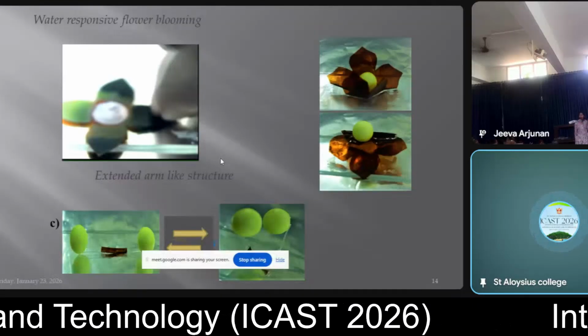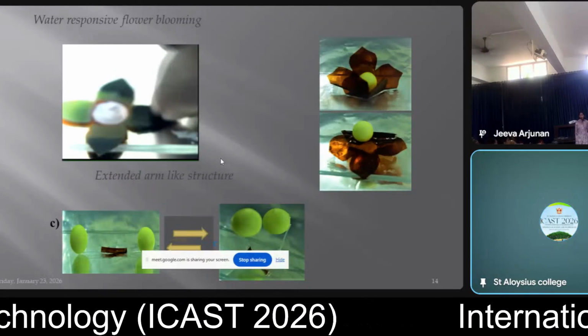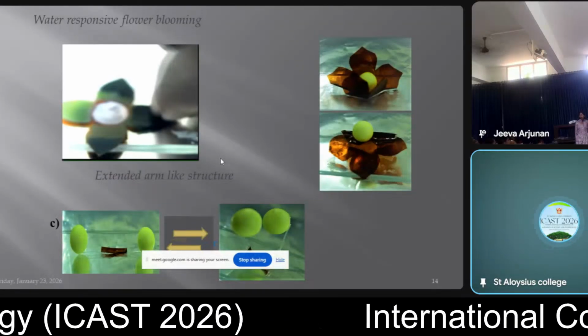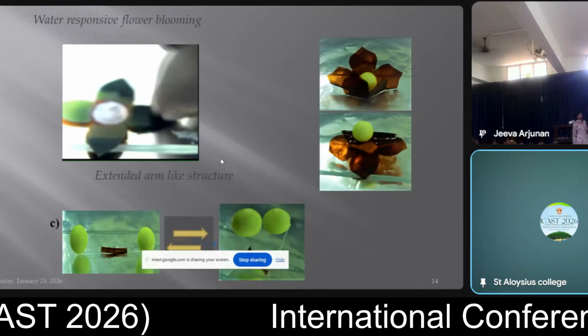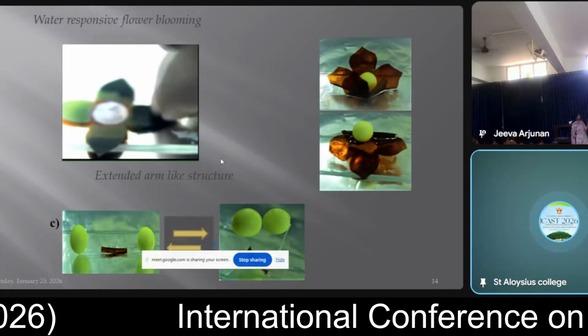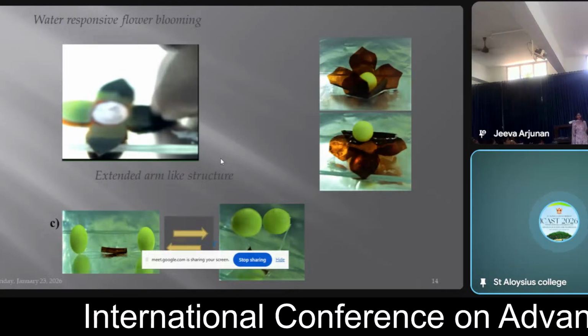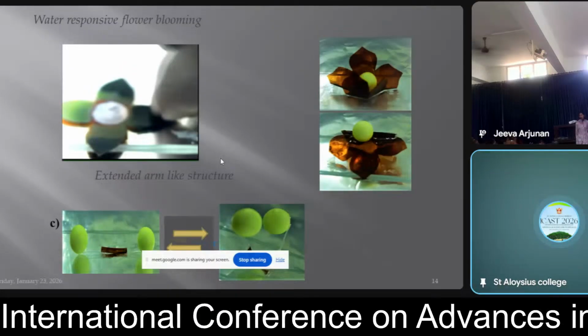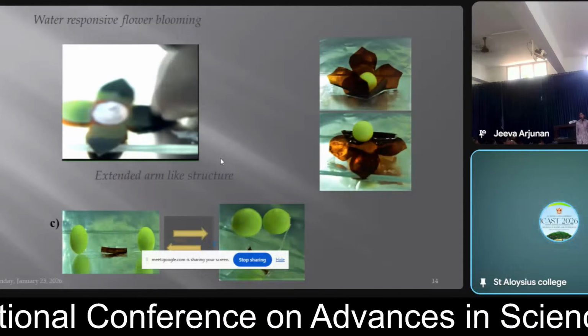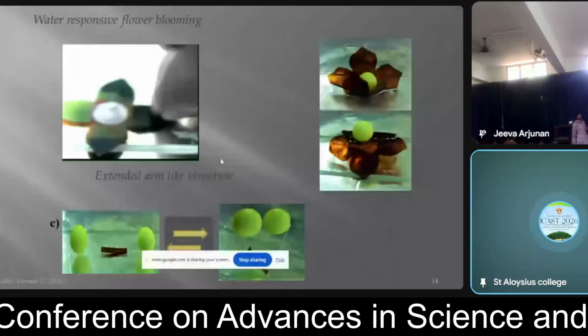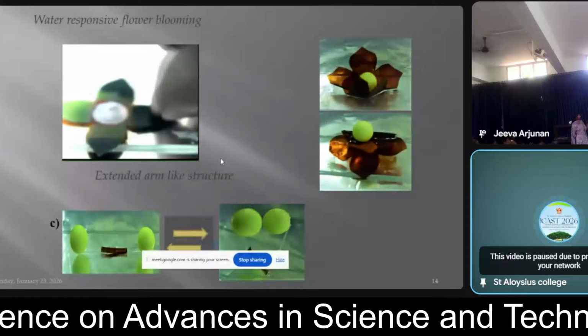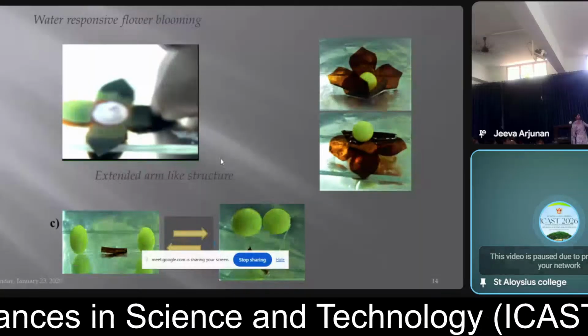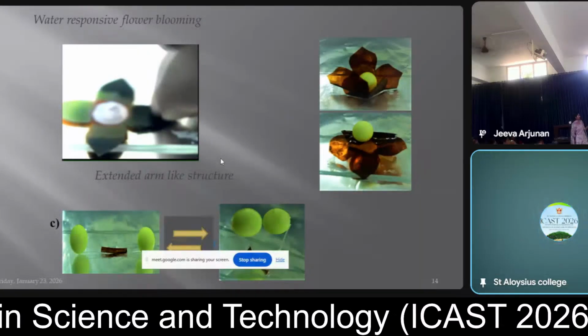We cut the chitosan-incorporated polyaniline film sheet into a flower shape, and then we put thermocol in the central part for weight, because it has low mechanical support. So when we apply water underneath, it starts to fold. That's what we are observing here.